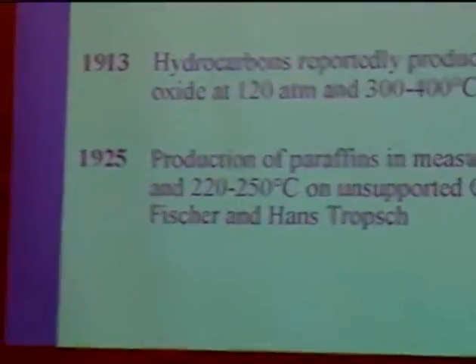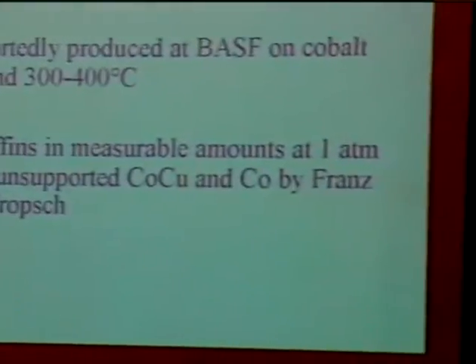In the years subsequent to this patent, we know that Hans Tropsch and Franz Fischer investigated the production of hydrocarbons on cobalt and other catalysts. In 1925 to '26, they announced the production of paraffins in measurable amounts at 1 atmosphere and 220 to 250 degrees centigrade on unsupported cobalt-copper and cobalt catalysts. These are definitely conditions under which we could say catalysis is taking place, with measurable quantities quantitatively reported in their 1926 patent.